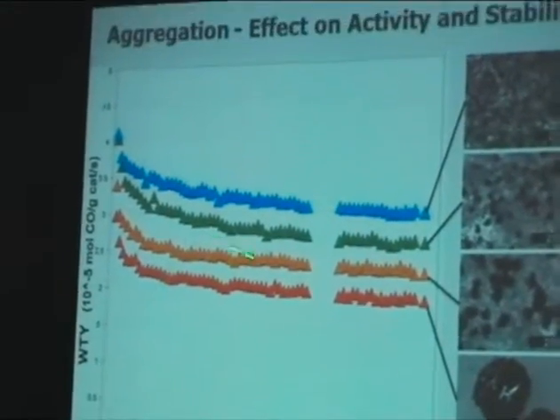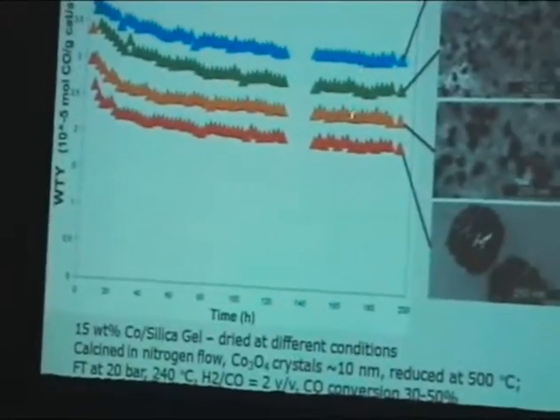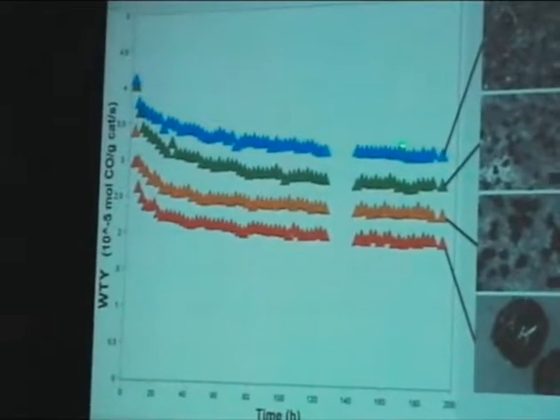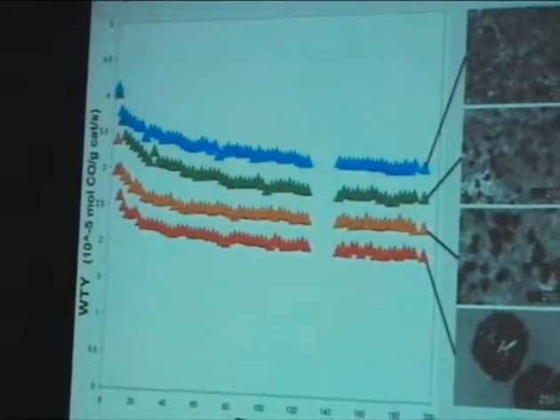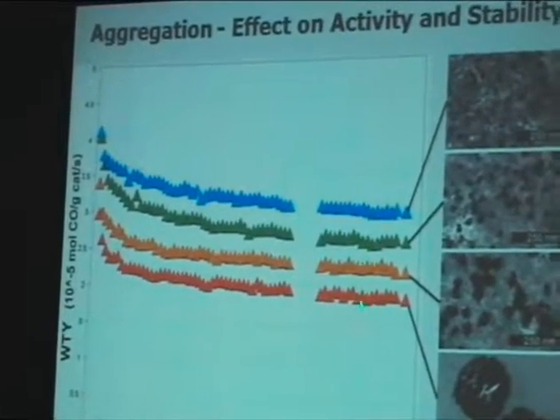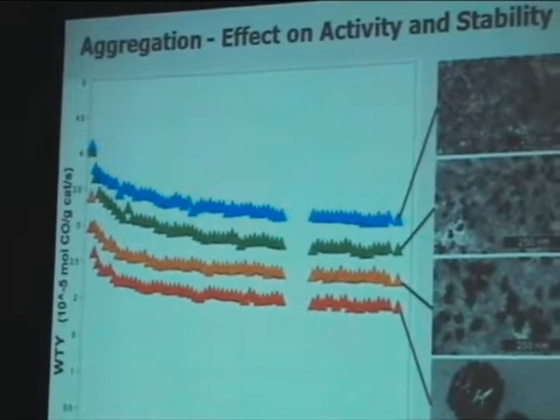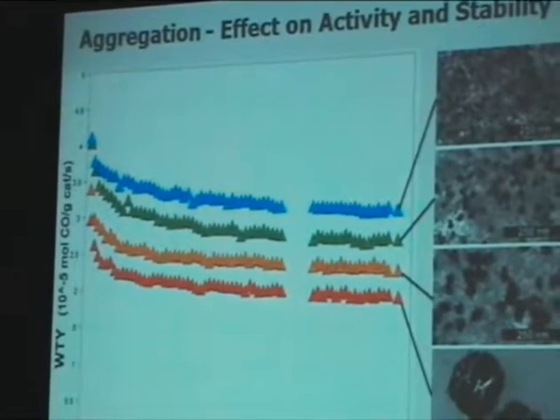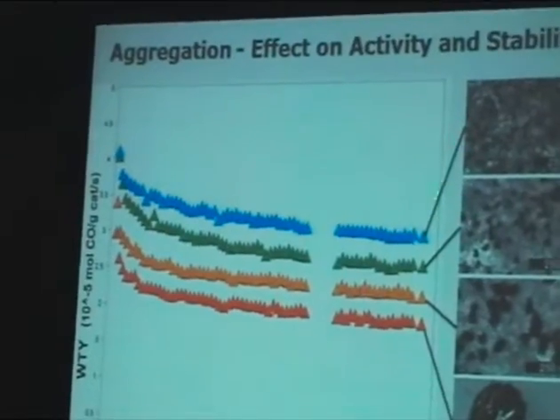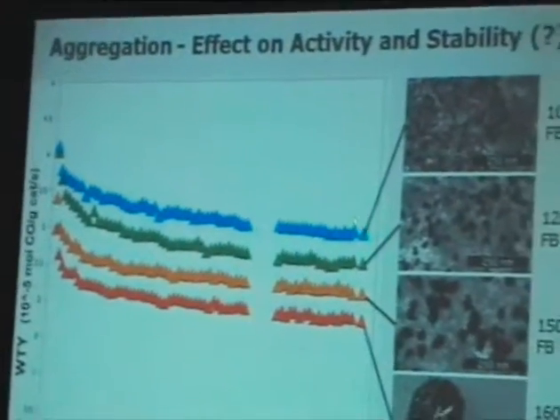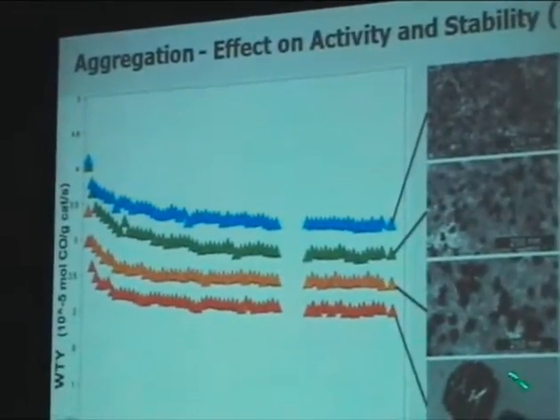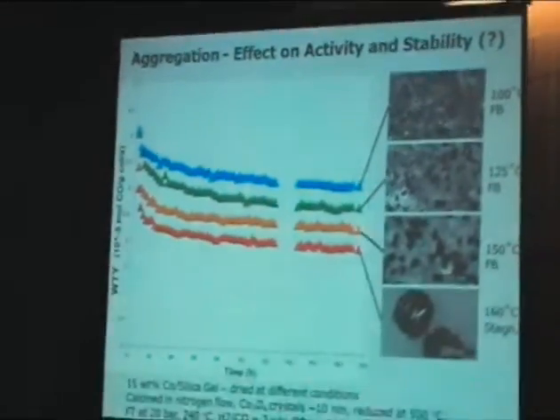So while the cobalt loading is the same, it is expressed per gram of catalyst. And what we see as a function of time is that there's a significant variation of both the initial and the almost steady state activity after some 200 hours. And clearly, with the isolated nanoparticles, you get significantly higher activities compared to the very large aggregates.